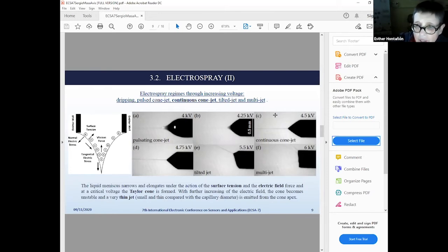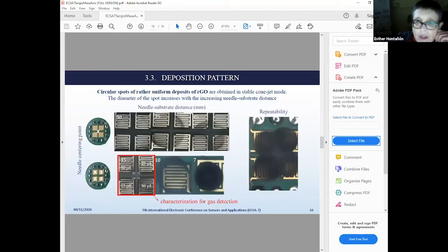We have found that in order to attain homogeneous and uniform deposits of RGO on the substrate, it's necessary to operate the electrospray in the continuous cone jet mode, which is the most stable one. Here you can see how the RGO deposit looks after electrospray, and what we finally found is that the size of the deposit of RGO on the surface of the substrate depends on several factors, but is mostly determined by the separation distance between the needle tip and the substrate.